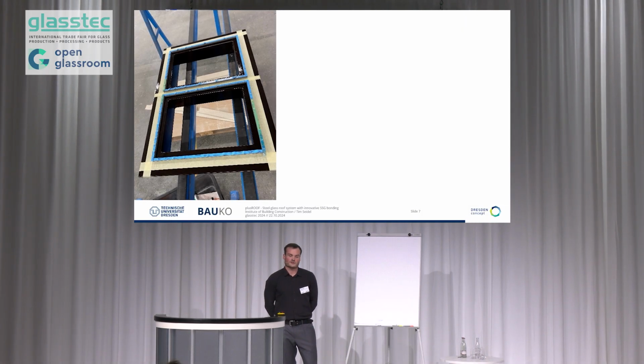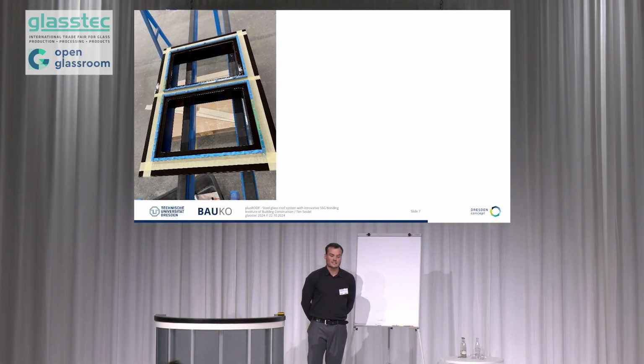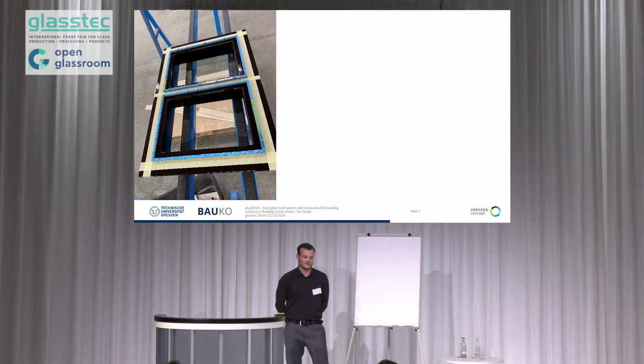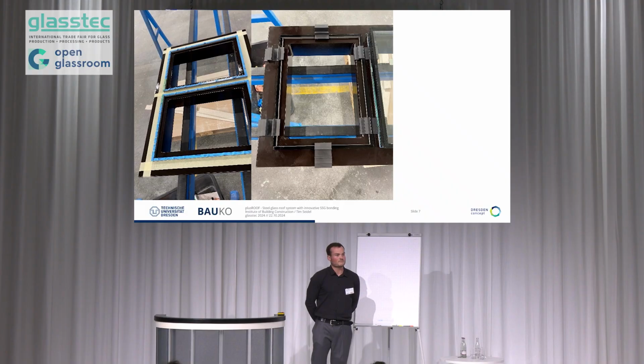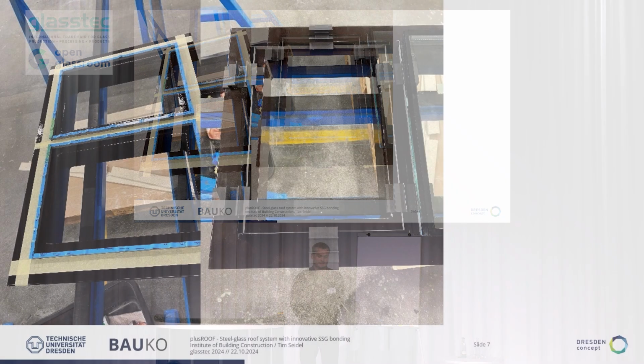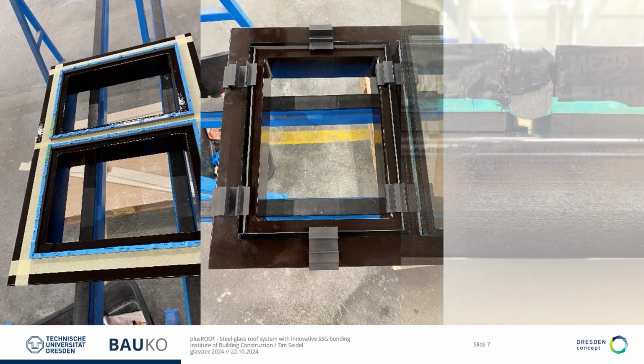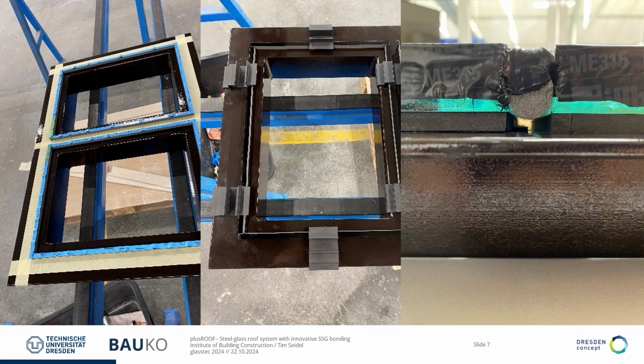We used the results from the small part tests to produce steel glass roof elements in component size to test their practical feasibility. The first sample, measuring 300 times 400 millimeters, had two rectangular insulating glazings. These glazings were not inclined.